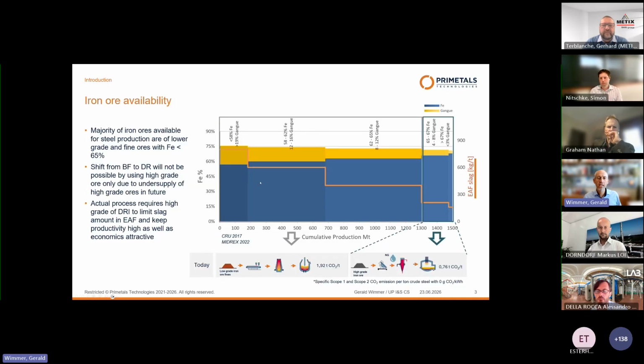If we have a quick look into the raw material side, here's a typical diagram. Primetals is using this since quite some time, so you might already know it. So we see here the global produced iron ores, transported ones, 1,500 million tons a year, an incredible amount. And you see on the vertical axis the iron content in blue and the gangue content in yellow. And of course, the gangue in the classical route using electric arc furnace is becoming slag. So the higher the gangue content, the higher the slag amount.